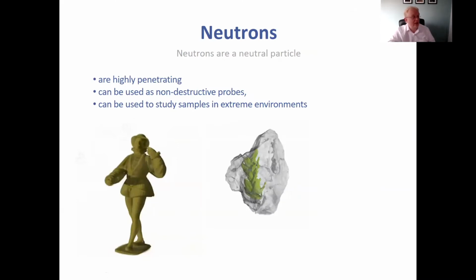Well, neutrons are highly penetrating, which means they can see through things very easily. They are non-destructive, so you will not damage your material in any way with a neutron, and they can be used to study samples in extreme environments. And the reason they can do that is because we can encase our sample of interest in a complex sample environment that can be made out of high tensile steel. We can heat it up to very high temperatures and very high pressures. And if we do the experiment properly, all we'll see in our neutron experiment is actually our sample of interest.